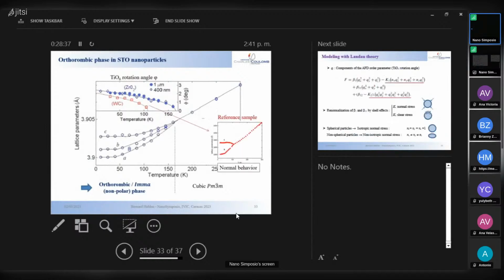And so for the normal sample, you have exactly what you expect, a cubic to tetragonal transition, as I've shown you in the introduction. But here in that sample, you have a development of a third lattice parameter, and we found that it is an orthorhombic phase. So by grafting the surface of the grain, we change the structure of the core of the grain.